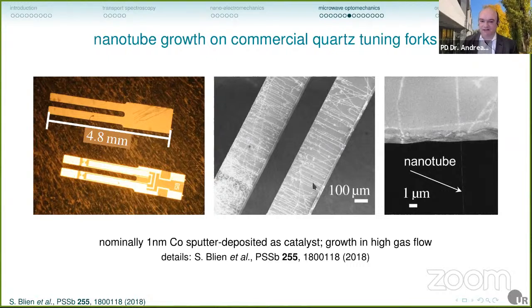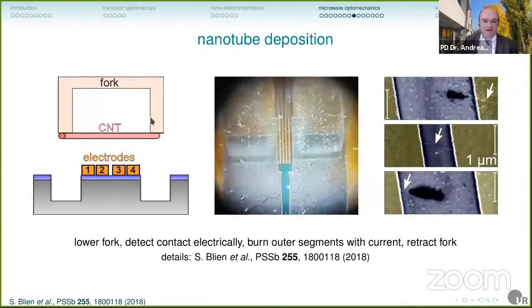And you can see they grow in a very straight fashion, and they cross the gap here between the two tines. And then we can take our tuning fork and lower it down onto the electrodes, and at some point we touch the electrodes and we get electrical contact. And then we can apply a large voltage between contacts 1 and 2, and a large voltage between contacts 3 and 4, and burn away the nanotube there, like this here. We can retract the fork, and then we have our nanotube crossing the center gap between electrodes 2 and 3.